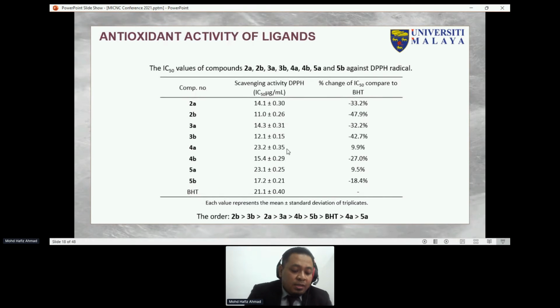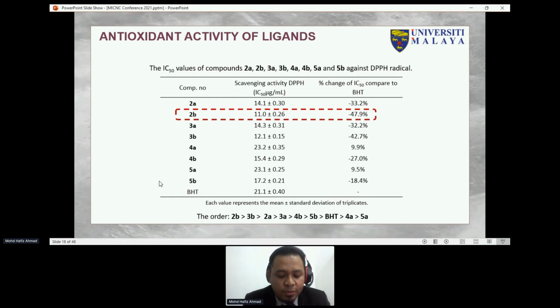Next, this data shows antioxidant activity of BHT ligand before functionalization with gold nanoparticles. All compounds show potent activity compared to BHT, except compound 4A and 5A. Among them, compound 2B is the most potent compound with a 47.9% decrease of IC50 value compared to BHT.